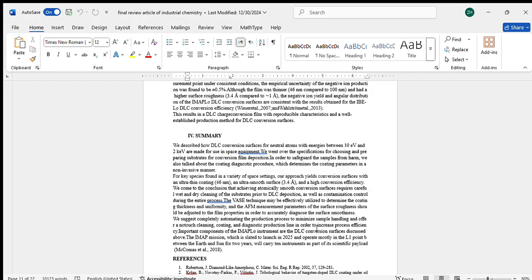DLC conversion surfaces for space use. The DLC coated conversion surfaces are designed for detecting neutral atoms with energies between 10 electron volts and 2 kiloelectron volts in space instruments. These surfaces are an important part of the IMAP mission payload. Coating and substrate preparation: the substrates used for the conversion surfaces are carefully prepared and cleaned to ensure the DLC film adheres well and provides the desired performance. The coating procedure was non-invasive, allowing diagnostic measurements without damaging the surfaces.